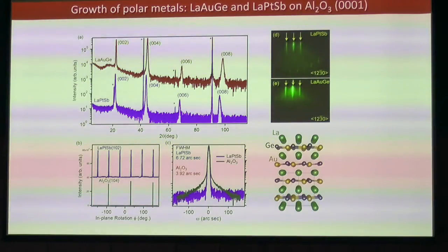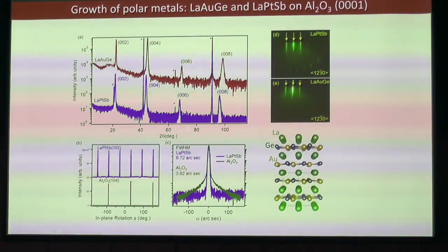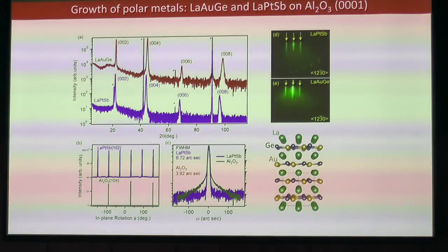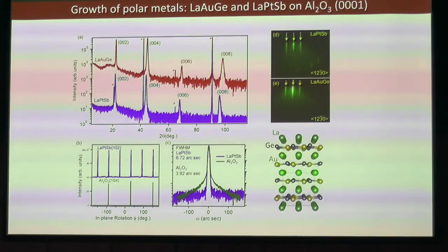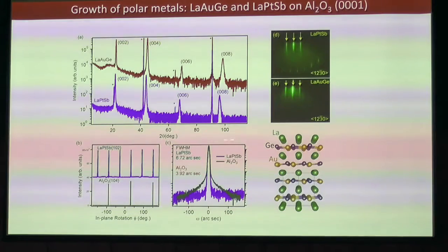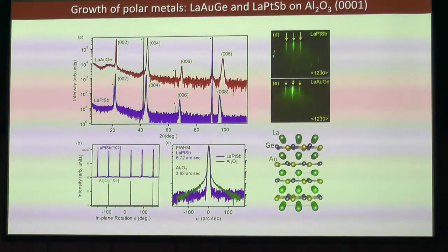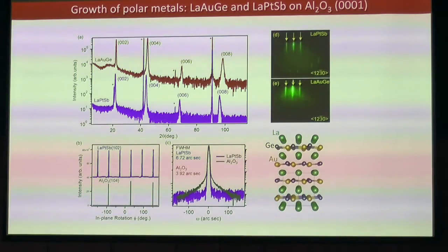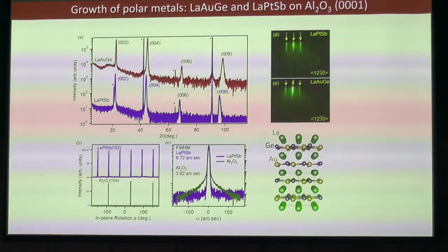So we started out by choosing 2 compositions, lanthanum gold germanium, lanthanum platinum antimony. We chose them because they're natively metallic. They're not magnetic, so it's a little bit easier to think about. And we've chosen to grow these on sapphire substrates. So you can see they're single crystalline at the level of X-ray diffraction. They're reasonably flat surfaces by reflection high energy electron diffraction. And they're singly oriented and have reasonably sharp rocking curves.